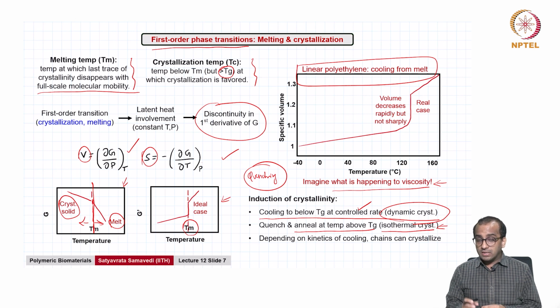When earlier I said for semi-crystalline polymers, the amorphous domains over time can relax with storage, this is an example of what is happening here. At specific storage temperatures, if it so happens to be above the glass transition temperature of the polymer, even if you are storing it very carefully at a fixed temperature under controlled conditions, the amorphous regions can relax and you can start forming crystals.